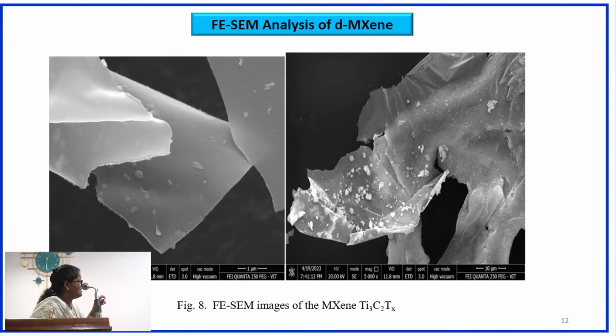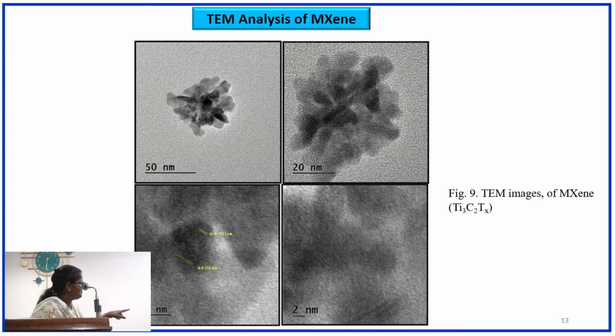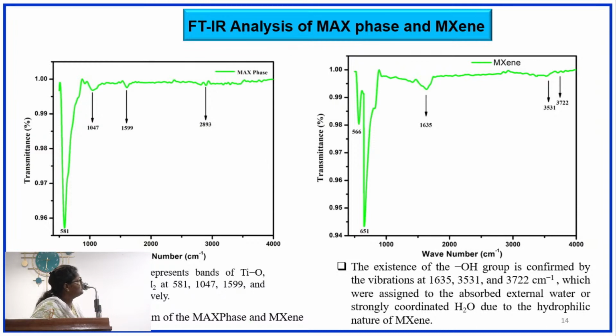We are the first to synthesize MXene using the electrochemical etching method at room temperature. We synthesized a single layer of MXene material, and this is the TEM analysis. The d-spacing of each layer is 0.37 nanometers. This is the FTIR analysis of the MAX phase and MXene. After electrochemical etching, there is an indication of OH groups, confirmed by vibrational wave numbers at 1,635, 3,531 and 3,722, indicating absorbed external water strongly coordinated with OH due to the hydrophilicity of MXene, which is very important for any material to have a hydrophilic nature.